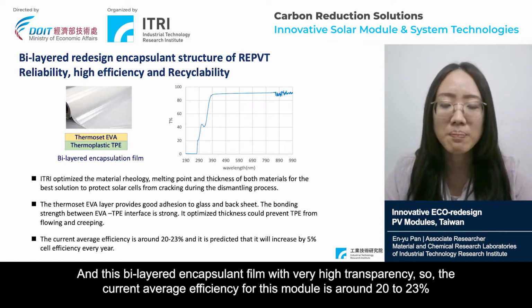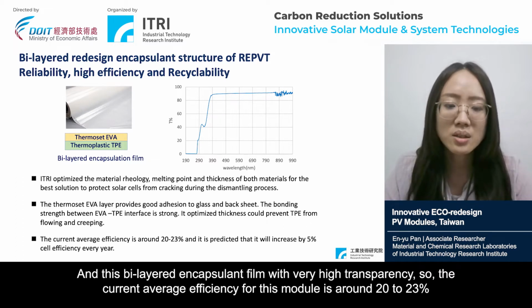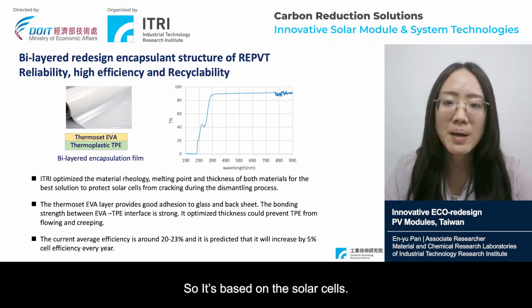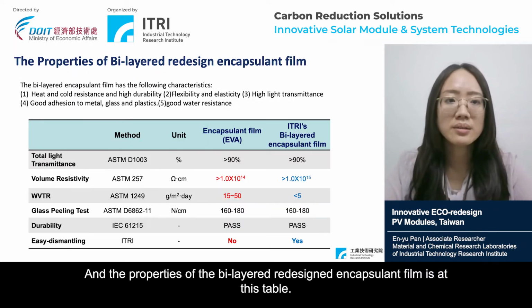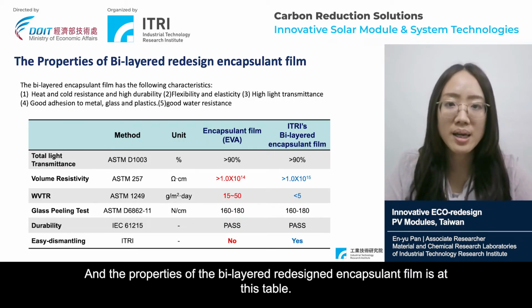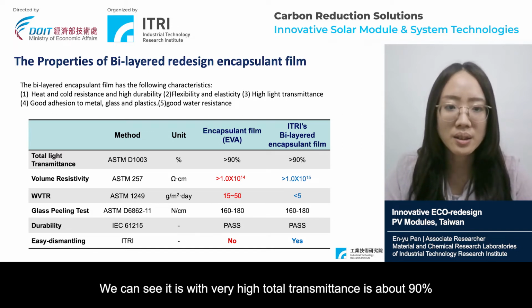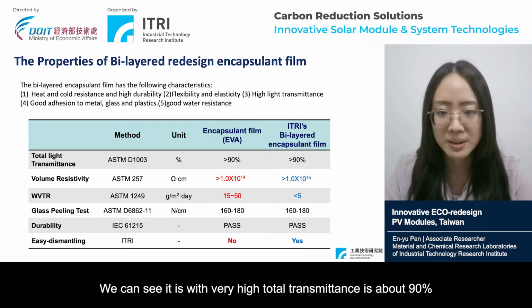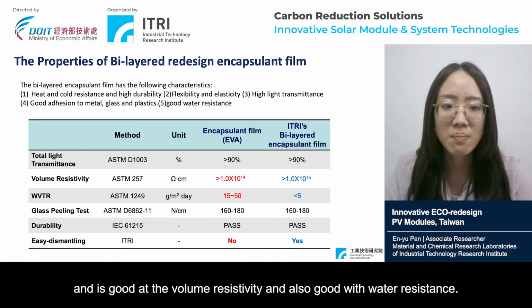This bilayer encapsulation film has very high transparency. The current average efficiency for this module is around 20 to 23%, based on the solar cells. The properties of the bilayer redesigned encapsulation film are in these tables. We can see it has a very high total transmittance of about 90%, and it is good at volume resistivity and also good at water resistance.